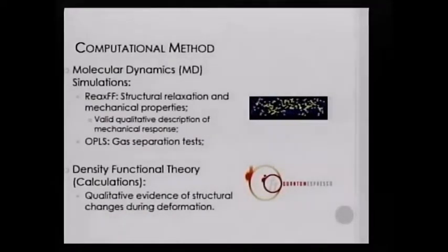We chose ReaxFF because in our earlier works we found that overall the qualitative description of tensile strain is adequate, even if the overall values ReaxFF displays for stress and strain are overpredicted. Also, we employed the OPLS parameters for some gas mixtures and carbon materials to perform gas separation tests, which will be explained further on.